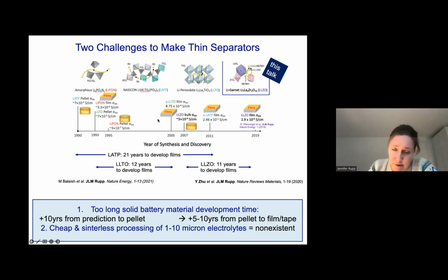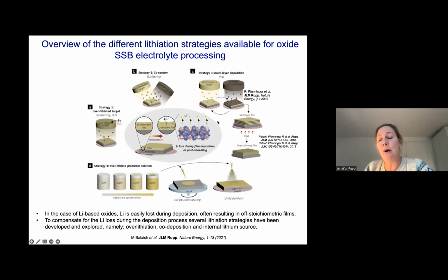And the answer to all of it is that it takes the whole field, all the scientists, all the engineers in the world, 10 to 15 years just to get something from the pellet processing to the thin film in the right lithiation level and the right conductivity. And we can see that here in several examples for almost all the chemistries except for LiPON. And the reason is, why does it take actually so long to make a pellet chemistry, for instance, a ceramic electrolyte, into a thin film chemistry?